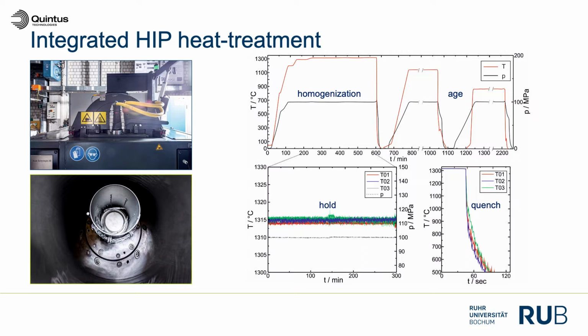Yeah, sure. So the integrated HIP heat treatment, or the high pressure heat treatment, is of course very beneficial when it comes to the processing itself. We can perform the heat treatment and the hot isostatic pressing in one single step. When it comes to nickel-based single crystal superalloys, this means that we can perform the solution annealing, which is a very extensive and very careful heat treatment, and simultaneously apply pressure in this process. Then we can homogenize all these chemical inhomogeneities, but also shrink the porosity in one single processing step. And this, of course, saves a lot of time and money, and we have a beneficial effect on the mechanical properties, because in the end, after the solution annealing or the holding step, we can quench down very rapidly.